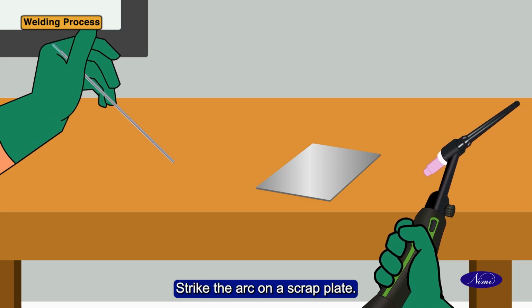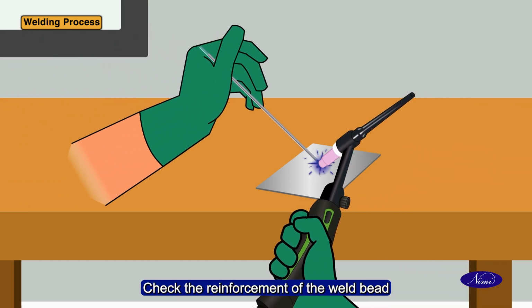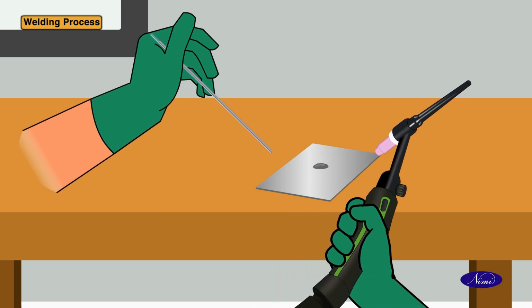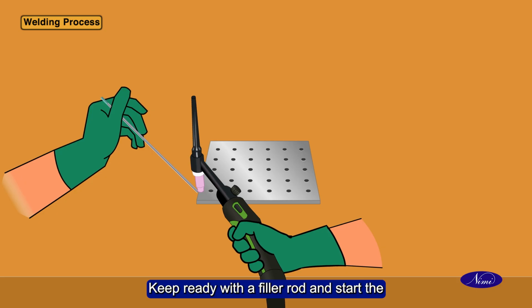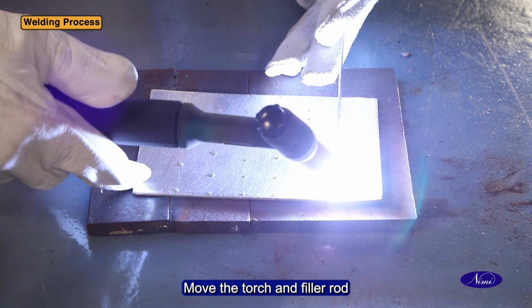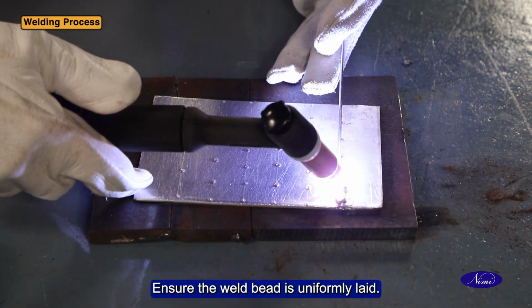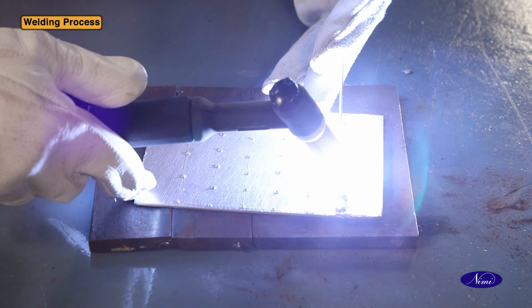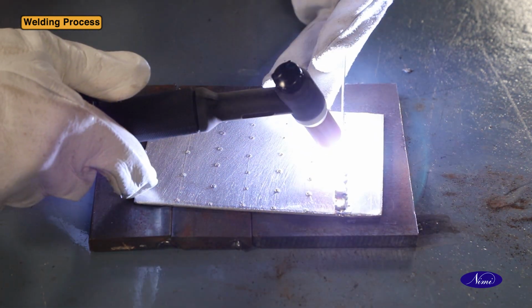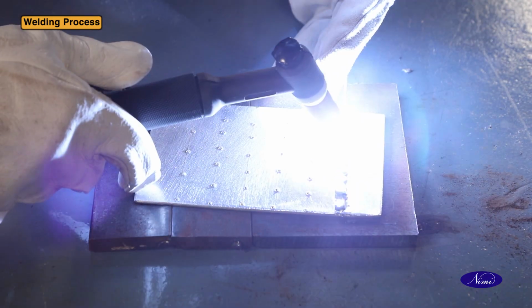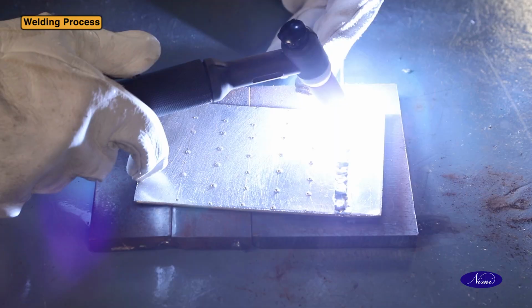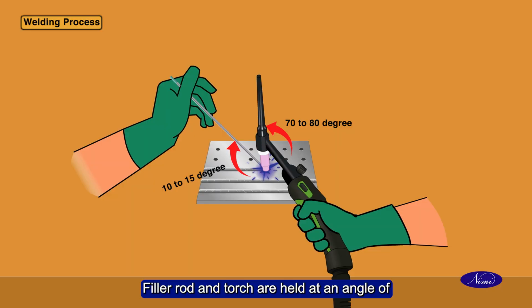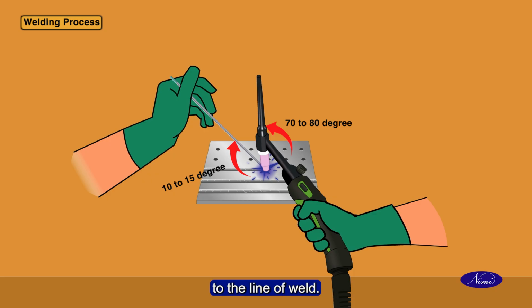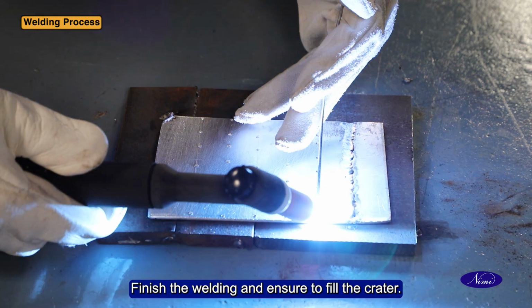Strike the arc on a scrap plate. Check the reinforcement of the weld bead and ensure that the correct width is maintained. Keep ready a filler rod and start the welding from the first punch marked line. Move the torch and filler rod at a uniform travel speed. Ensure the weld bead is uniformly laid. Filler rod and torch are held at an angle of 10 to 15 degrees and 70 to 80 degrees to the line of weld. Finish the welding and ensure to fill the crater.